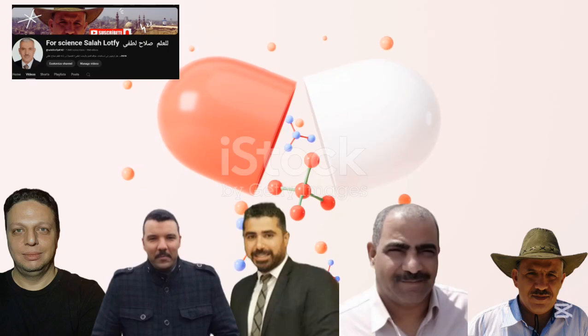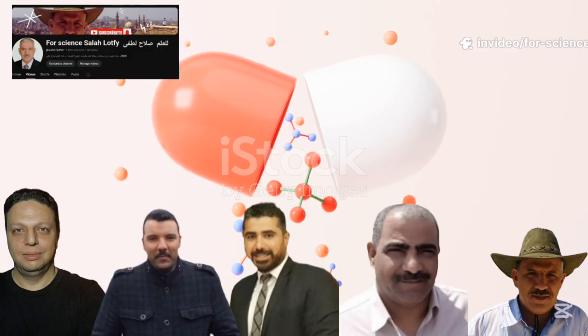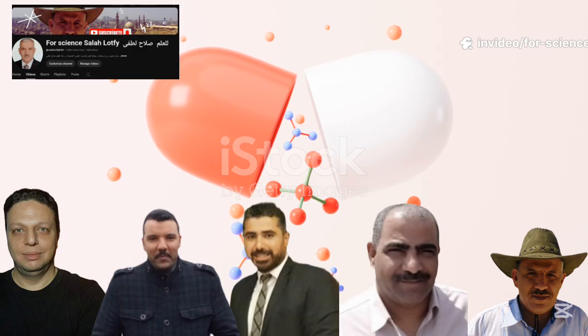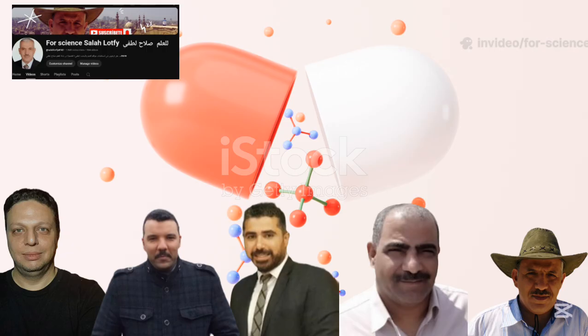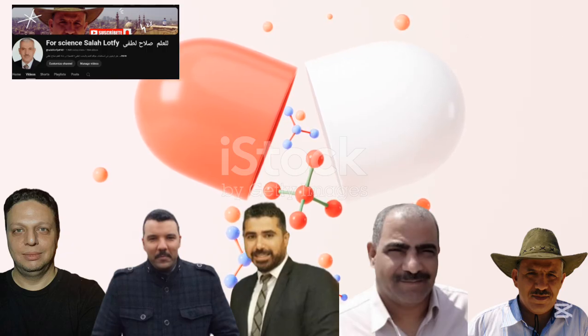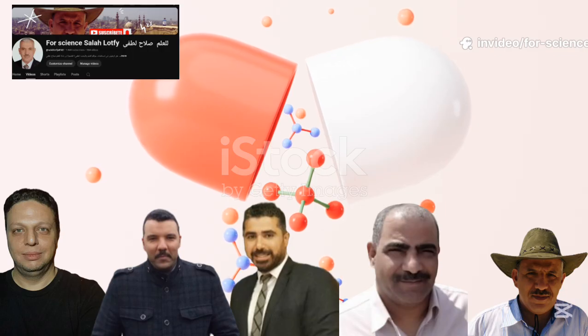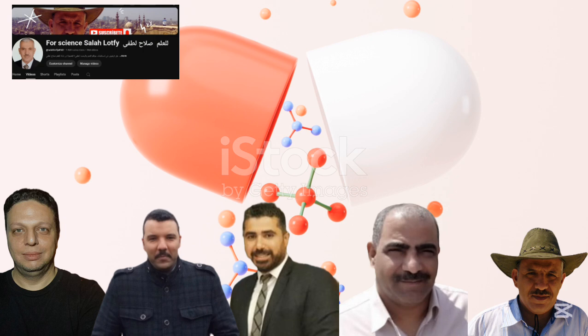This complex structure gives rise to an astonishingly high surface area, over 72 square meters packed into a single gram of material. To put that in perspective, that's like unfolding the surface area of a large classroom and compressing it into a pinch of powder. This immense surface area is critically important. It dramatically enhances solubility, as there are far more points of contact for a solvent to interact with the material. For biomedical applications, this means a drug loaded into the material can dissolve more readily in bodily fluids.